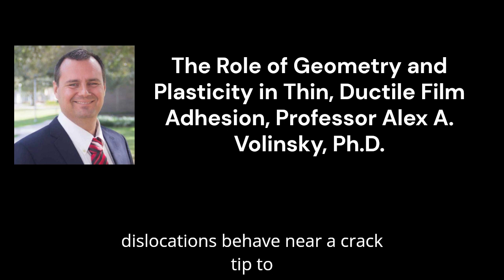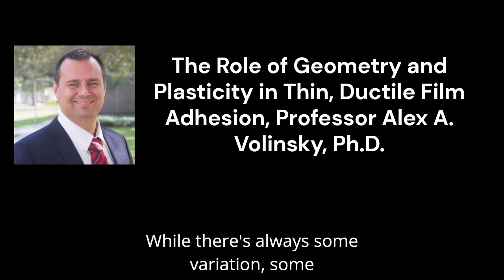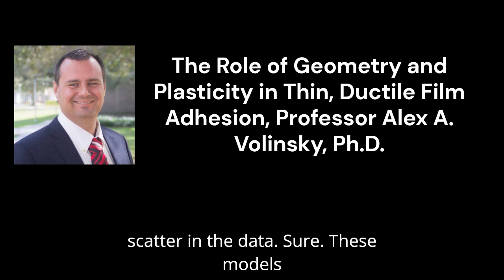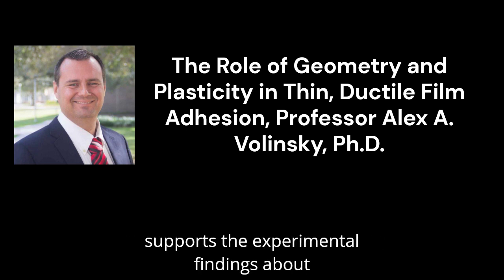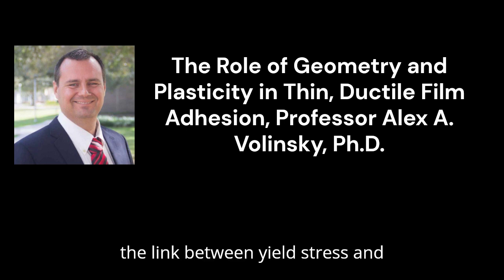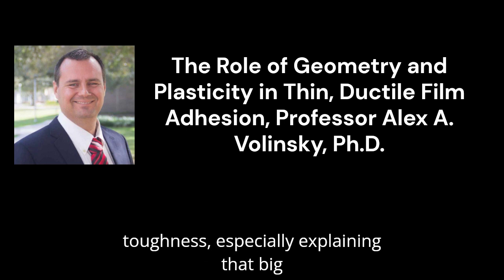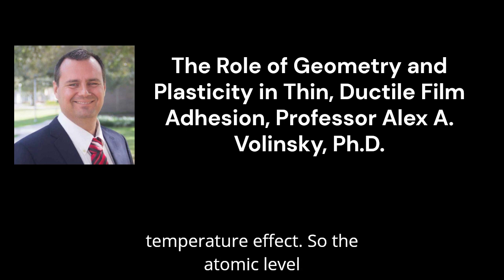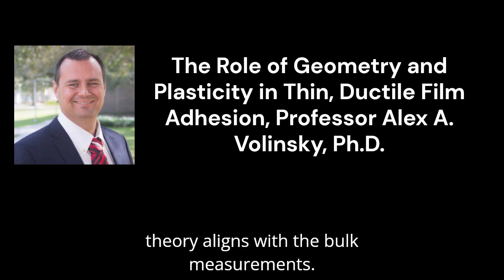Exactly. How those dislocations behave near a crack tip relates to the macroscopic toughness we measure, while there's always some variation, some scatter in the data. Sure. These models provide a theoretical framework that supports the experimental findings about the link between yield stress and toughness, especially explaining that big temperature effect. So the atomic level theory aligns with the bulk measurements.